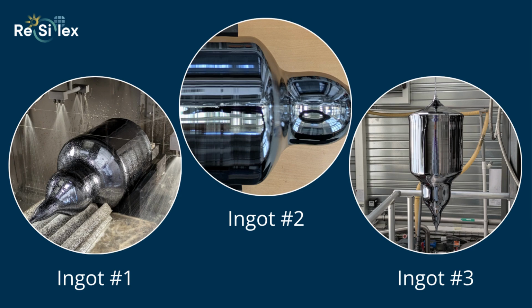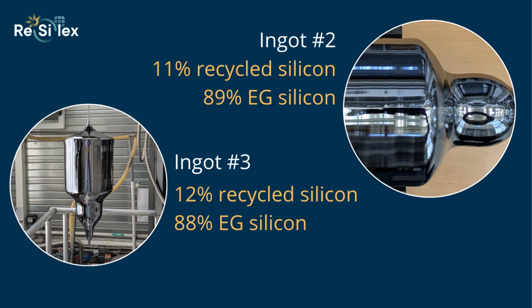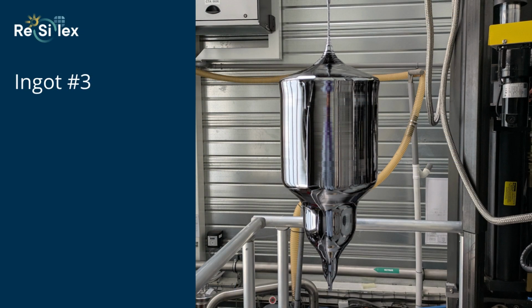In total, 3 CZ ingots of 30 kg were pulled by CEA using this novel feedstock. For the last 2 ingots, blending was conducted with respectively 11% and 12% of recycled silicon and 89% or 88% of electronic-grade silicon. The last ingot of 30 kg was pulled free of dislocations.